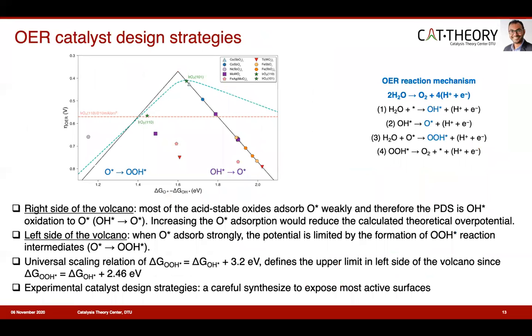So a one-dimensional OER activity volcano that includes thermodynamic overpotential and the ΔG_O minus ΔG_OH descriptor for the most promising acid-stable catalysts is shown here. And we can see that the potential determining step for most of the inactive surfaces is OH oxidation to O, which is on the right side of the volcano. This indicates that O adsorbs weakly on these surfaces, and by increasing the O adsorption, we could reduce the calculated theoretical overpotential. Whereas on the left-hand side of the volcano, the oxygen adsorbs strongly, and therefore the potential is limited by the formation of OOH.